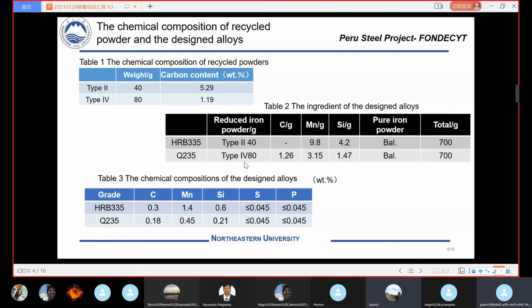Now, you add carbon, okay, pure iron. When you say pure iron powder, BAL, what does BAL mean? BAL means, okay, we need to prepare 700 grams in total, and we add 40 grams of recycled reduced iron powder, and we add the manganese, silicon, and others. The rest is the BAL, which means the balance. Balance means left. For example, 700 minus 40 minus 9.8 minus 4.2. It's a balance.